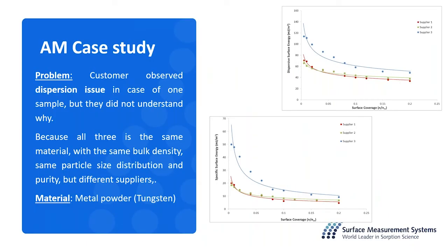There's another case study on additive manufacturing. In this case, it was a metal powder. The customer had an issue with one supplier batch, even though it was the same material, same density, same purity, all the physical properties were the same, but they had a dispersion issue with one specific supplier product. They sent it to us, and we measured the surface energy heterogeneity. And you can see that supplier 3 has much higher surface energy, significantly higher, and also the distribution of the surface energy is higher. So again, surface energy distribution has an effect on flowability, dispersion, dissolution.